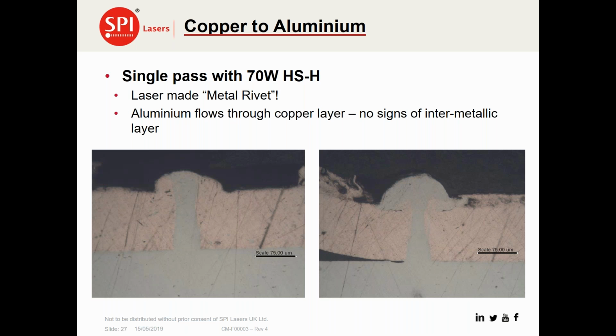So staying with copper to aluminium, this is an example of using a 70 watt HS-H laser for the same application. This is a really intriguing cross section. What we're showing here is a cross section whereby, again, we've effectively drilled through or cut through the copper layer, created a melt pool in the aluminium below, and you can actually see, probably by capillary action, the flow of aluminium up through the cut, which is creating almost a rivet-like structure in the joint. This is really innovative. You're not seeing any alloying, no intermetallic zone, and it really is a mechanical bond here.